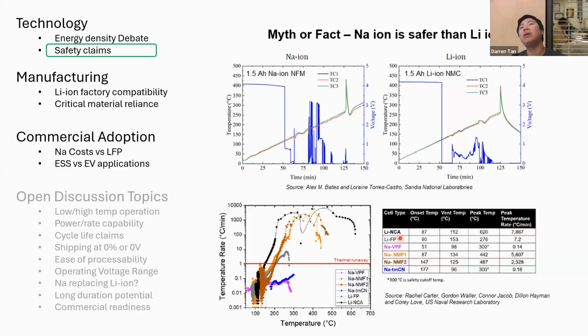Whereas the LFP one was very mild. It was only 7.2 degrees a minute. This is the gray one, the LFP cell. They define this line as the thermal runaway point, 1 degree a minute. It's arbitrary, but it's just a general guideline. So the conclusion was that both lithium-ion batteries did undergo thermal runaway.